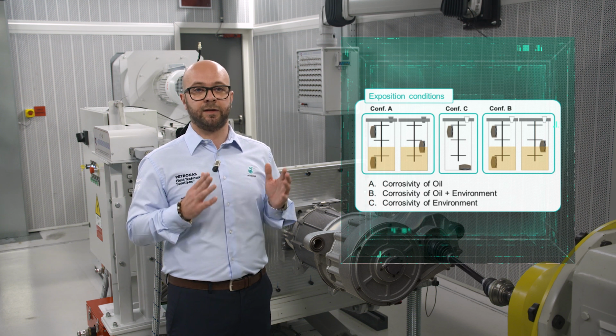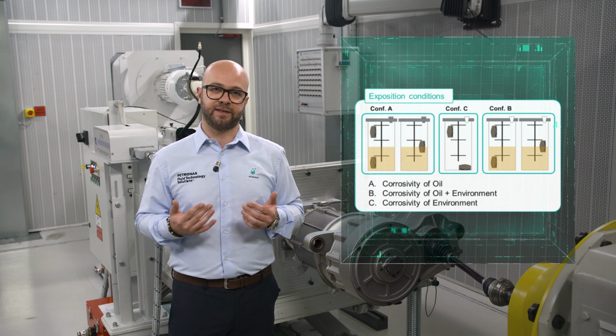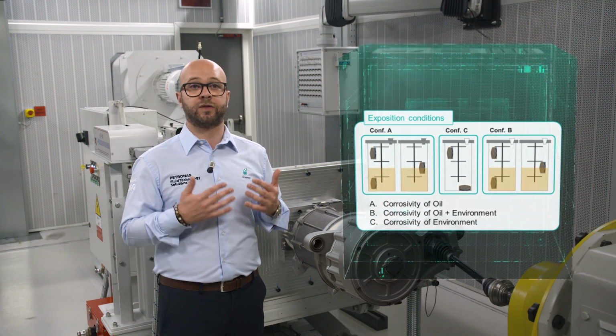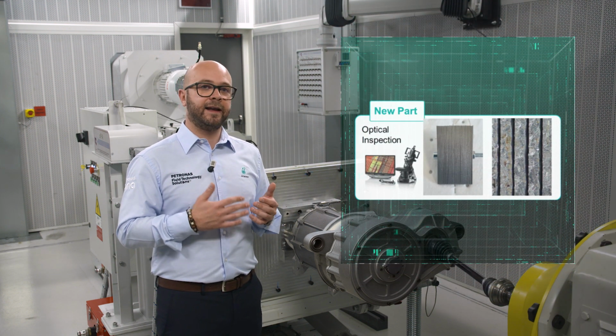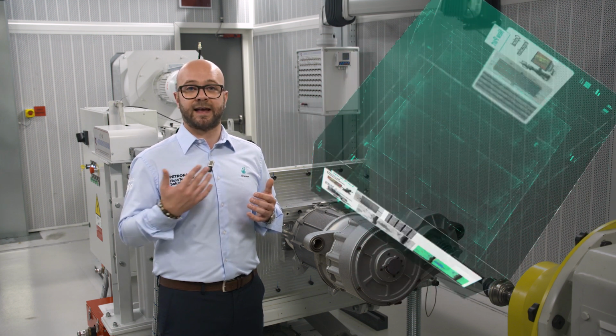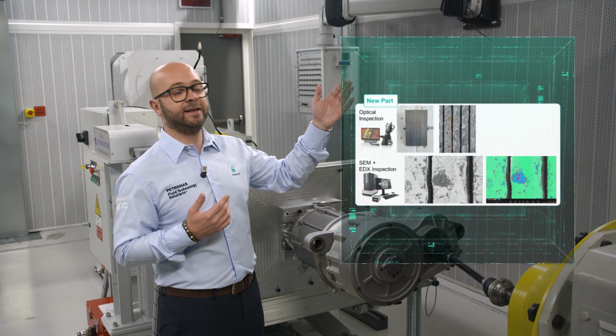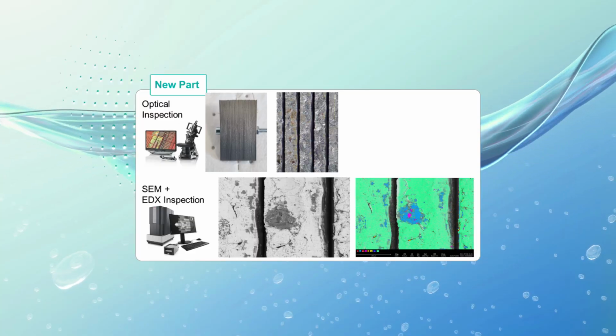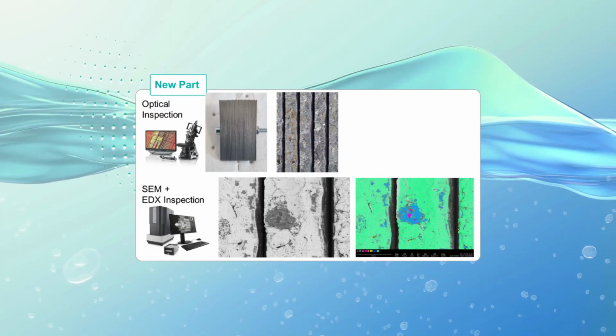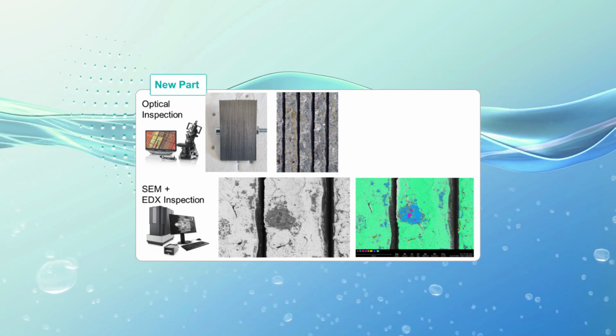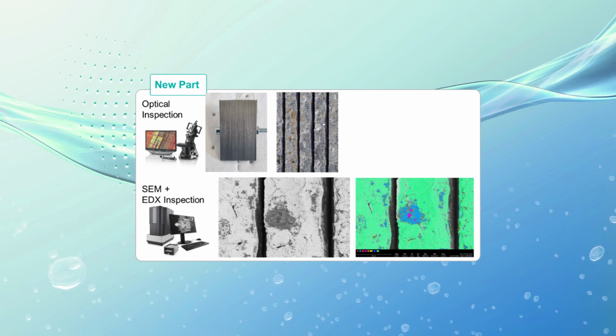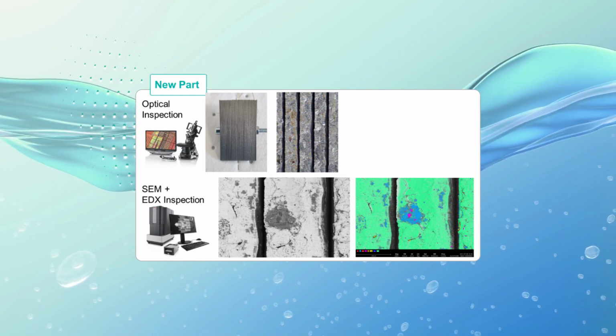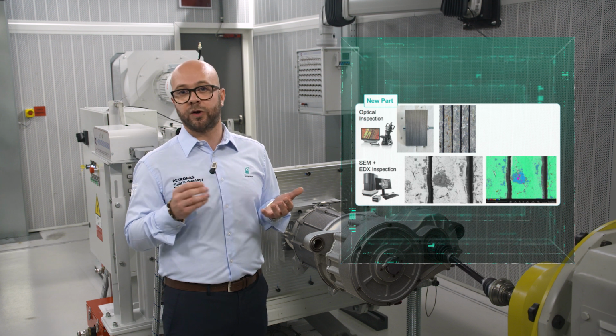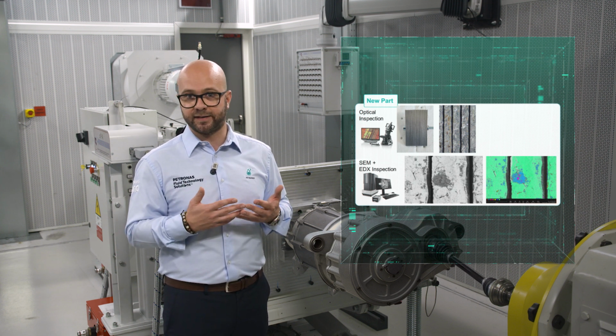For this type of test, which is carried out for several months, it is crucial to document the status of the surface in the pristine state. To do this, we carry out optical inspection of the part and inspection by means of scanning electron microscopy and also EDX mapping. The EDX mapping allows us to assess the condition of the surface, and in particular we see that the surface is clean. We have only the presence of an iron signal and some oxygen due to some points of rust that are already present in the pristine state.